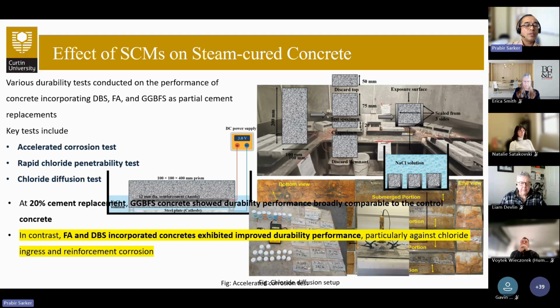What was done was we limited the percentage of SCM in the concrete for the test to 20% cement replacement, due to consideration that for precast concrete we need some minimum strength development in 1 day for demolding, and also good strength development for transportation of the units to the site—basically the early age strength development of concrete. So for that consideration, we limited the SCM content to 20%.